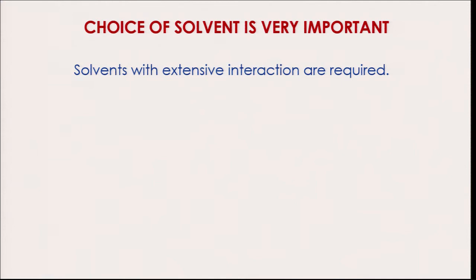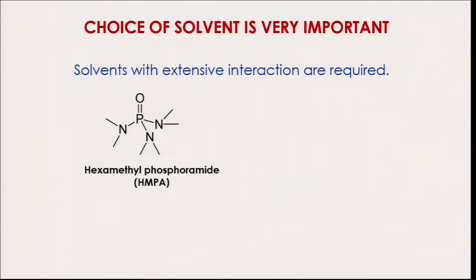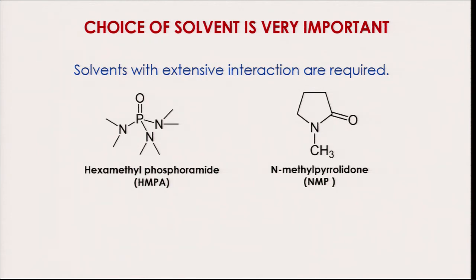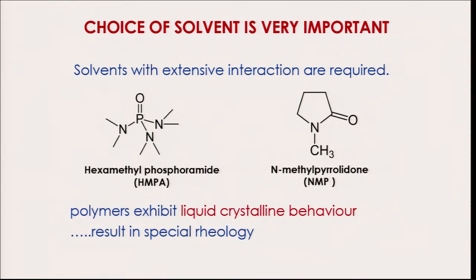Solvents with a very high degree of interaction are required, something like HMPA, hexamethyl phosphoramide, or NMP, N-methyl pyrrolidone. These are highly corrosive solvents, very difficult to handle. Or sulfuric acid, 100% sulfuric acid, not even 99.5, 100% sulfuric acid. So, these polymers exhibit liquid crystalline behavior when you dissolve them in these solvents,